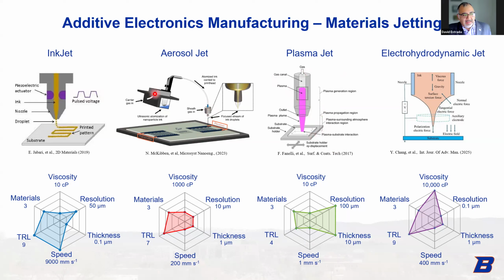Plasma jet works a lot like aerosol jet. Ultrasonic or megasonic atomizer, but at the print head, you end up going through a cold atmospheric plasma, which allows you to do plasma chemistry on your particles as they go through, helps dry the solvent, and the plasma can actually clean the substrate, charge the substrate, and improve adhesion as well.